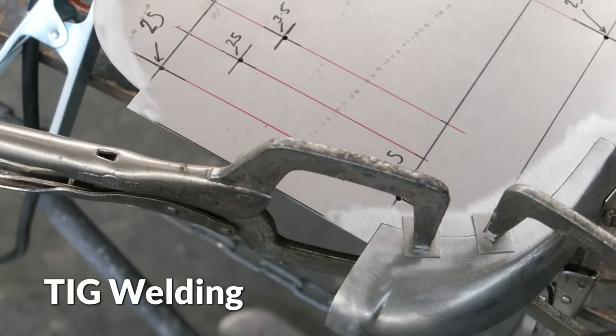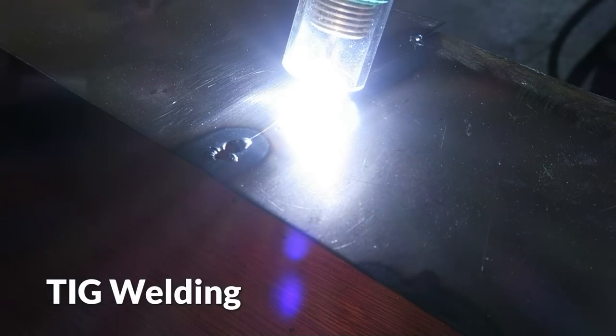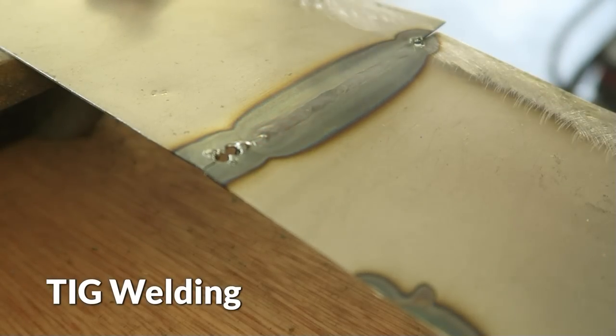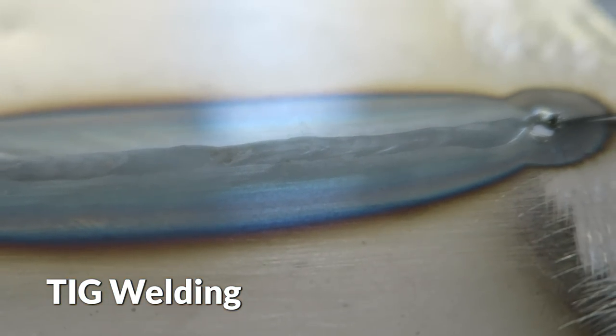When TIG welding, a really important point is that you're only adding the required amount of welding wire. The better you get your panels fitting together, the less wire you add. Perfect fitment means less gap, less filler rod, less welding time, and less clean-up. Many coach builders avoid using filler rod, resulting in the weld being undercut because the panel steel becomes the entire weld — the panel steel flows into the gap, resulting in a sunken weld.